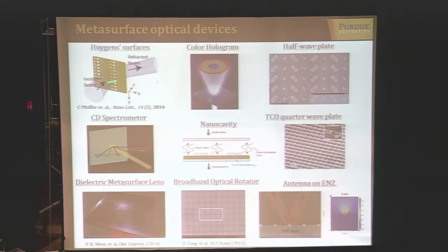This is, for example, a Huygens surface, where we control coupling not only to the electric field component but also to the magnetic one. By doing so, you could match the impedance and get rid of reflectance.